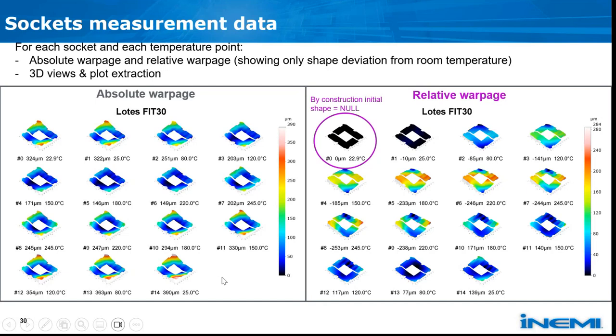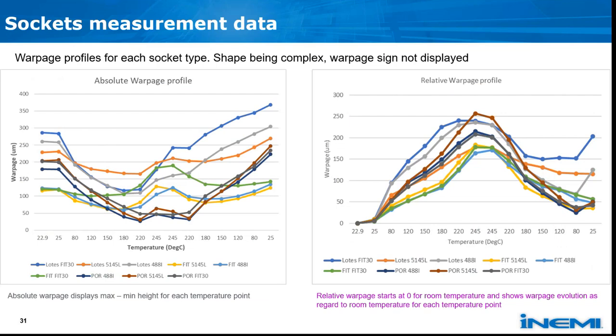We have another type of information we can provide, which is the relative warpage. The reason why we provide two types of information is because when we need to compare different samples altogether, we may have different warpages at room temperature. So while comparing different samples during thermal profiles, we might not know if the difference is due to the initial shape being different but the trend being the same, or that the behavior of each sample with regard to the thermal profile is different. So relative warpage allows us to annul the initial shape, to consider it as 0, and we just check the shape variation of each sample with regard to room temperature. Next slide, please.